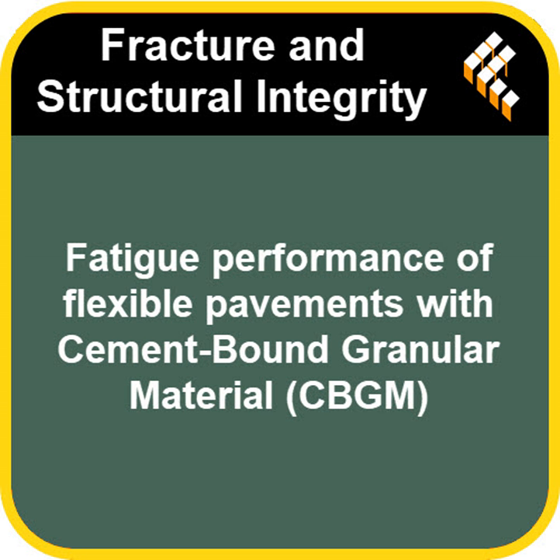Wow, and that huge difference brings us to the core of this mystery you mentioned. It does, because the 2014 Polish catalog for pavement design, which is a key design guide used there, made a really noteworthy assumption for these CBGM subbase layers. It entirely omitted the uncracked phase from consideration in its main design tables. It just ignored the strongest phase. Essentially, yes, for the standard calculations. For stronger CBGM mixtures, it just assumed a cracked state with small blocks already formed, which significantly reduces the assumed stiffness right from the get-go.